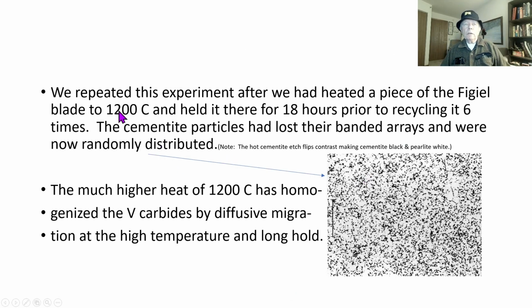So, we took a piece of the Figiel blade and heated it for 18 hours at 1200 centigrade. Now, this severe heating produced a huge change. After the 6 cycles, which we did following the heating, bingo, all the bands are gone. Cementite appeared as black little particles in a white matrix of pearlite after we used that etch. We think what's going on is that the much higher heat of 1200 has homogenized the vanadium particles, because at 1200 degrees they will diffuse much faster and can homogenize. And that's been shown by experiments to happen.